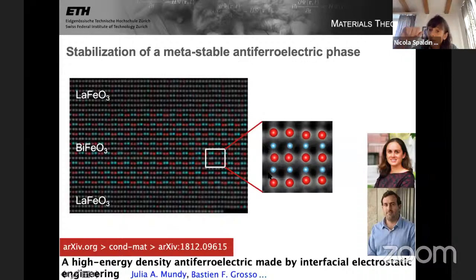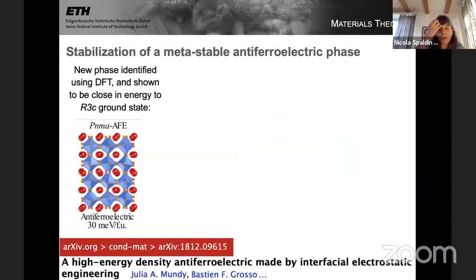And so this structure, if you just count the dipoles, this structure is antipolar, right? It has local dipoles. We can see that we have net displacement between the bismuths and the ions, but some of them are going in one direction and some of them are going in the other direction. So using density functional theory, Bastien Grosso was able to identify this phase. He was able to find a metastable phase, which from whichever angle we looked at it, when we compared it with the transmission electron micrographs, we saw the same patterns of the bismuths and ions. And he showed that this phase was rather low in energy relative to the ground state. It was higher in energy than the ground state, but not by very much. It was rather close in energy to the ground state phase.